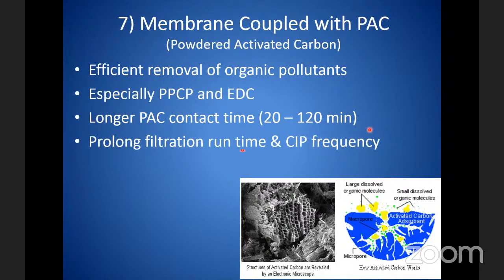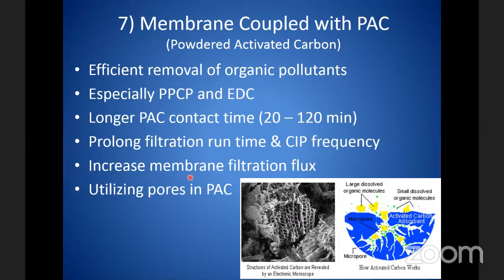So you also prolong filtration time and the CIP frequency. Why? Because the powder activated carbon also takes away those foulants that will block the membrane pores. So it increases membrane filtration flux, as we have discussed. It is further utilizing the pores in the powder activated carbon. If you have short detention time or short reaction time, the pores, the holes in the powder activated carbon are not fully utilized. It's even better with superfine powder activated carbon, SPAC. It gives even better results in this case.